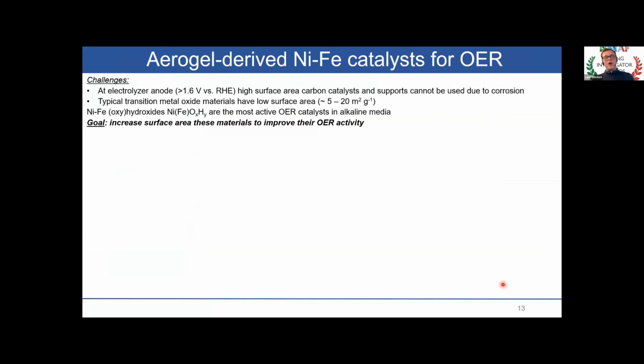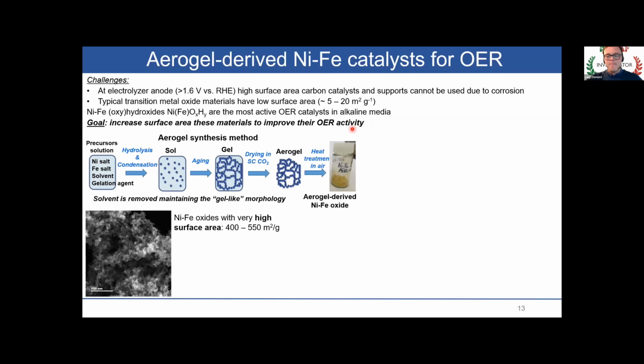The main challenge when we are talking about the oxygen evolution reaction, so the anode of this anion exchange membrane electrolyzer, is that we cannot use high surface area and conductive carbon materials because these will undergo oxidation. Also, we can only rely on transition metal oxides, which typically have a low surface area. So considering that the nickel iron oxide hydroxide are the most active OER catalysts in alkaline media, I tried to develop a method to increase the surface area and basically obtain a more active catalyst.